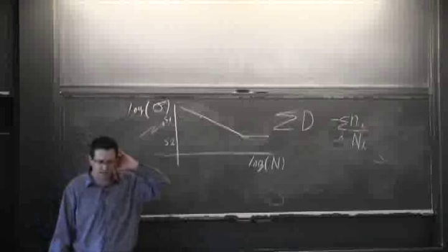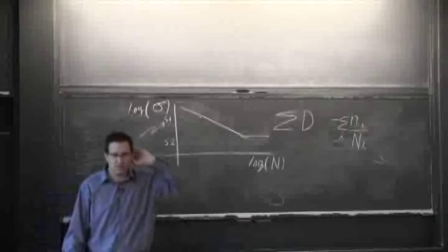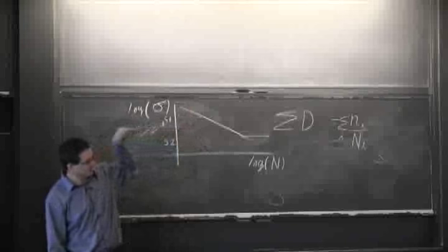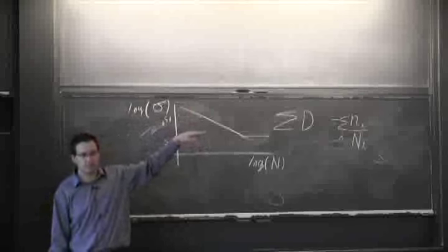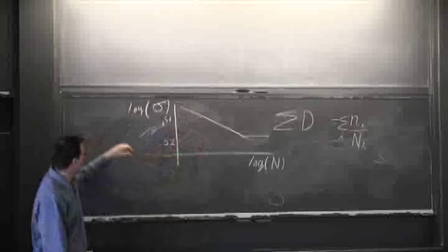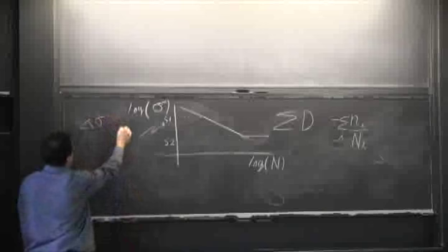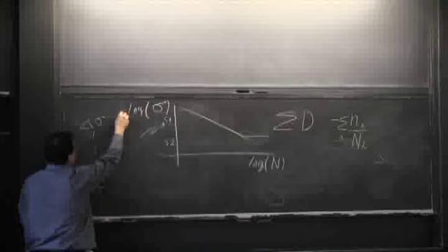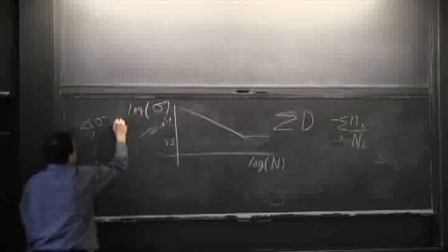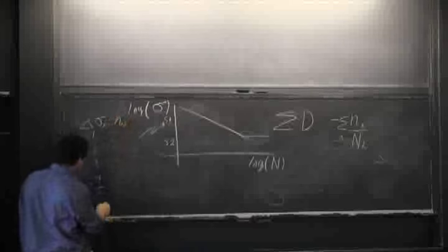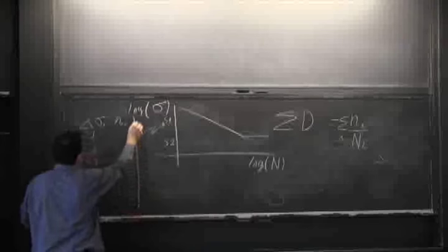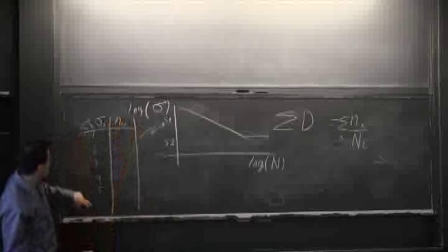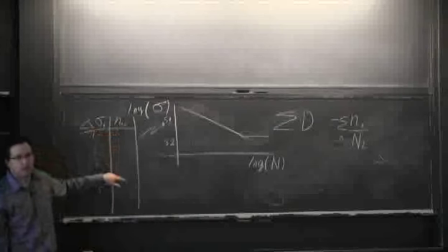Another method that's used a lot is the rainflow method. That essentially takes a random spectrum of load, and by projecting it in the horizontal direction, it looks for different amplitudes, and you can build a table that will tell you, okay, this is my delta sigma, starting with 1, 2. It will make a histogram for you, and this is how many cycles I have for it, we'll call it small n sub i. So you really end up with a very long list, this could be hundreds of lines, of different loading conditions with the number of times they show up in your overall spectrum.